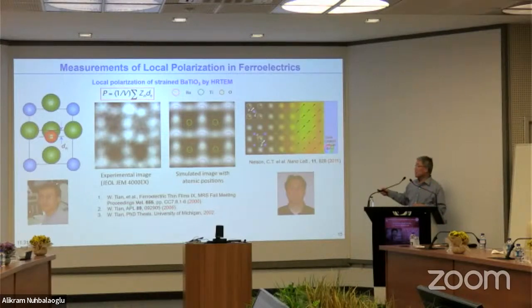And then we can determine the center of the positive charge and the center of the negative charge, and then we will know the type of movement for the unit cells. This is the way to determine the polarization, by determining the atomic displacement from unit cell to unit cell. This was done around 2000 to 2002, and then the next generation student, Chris Nelson, further developed this method using aberration-corrected TEM.